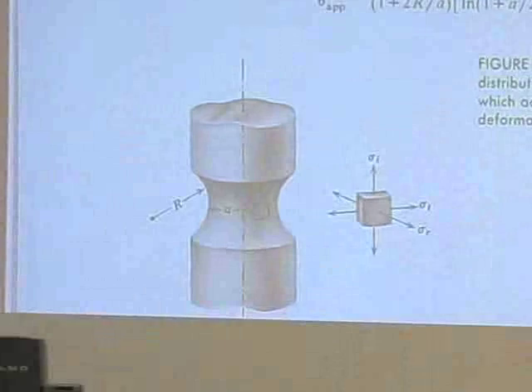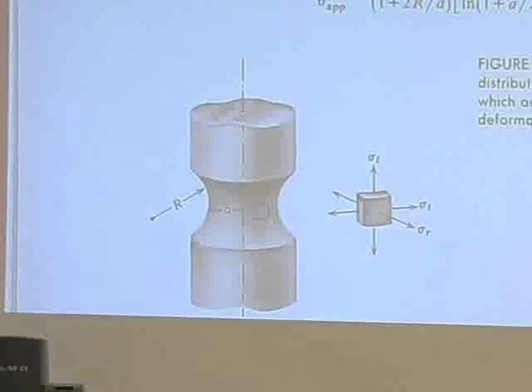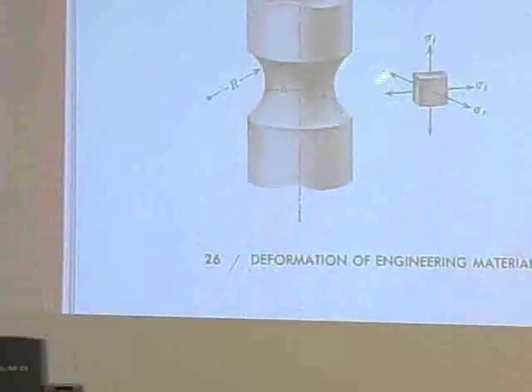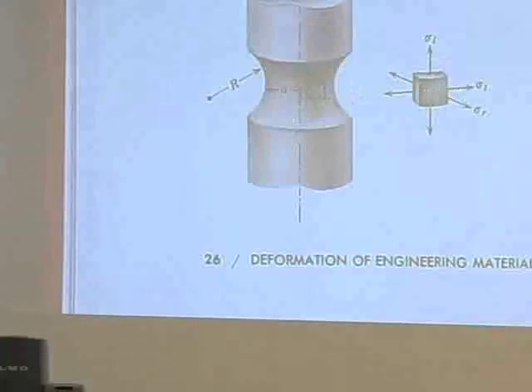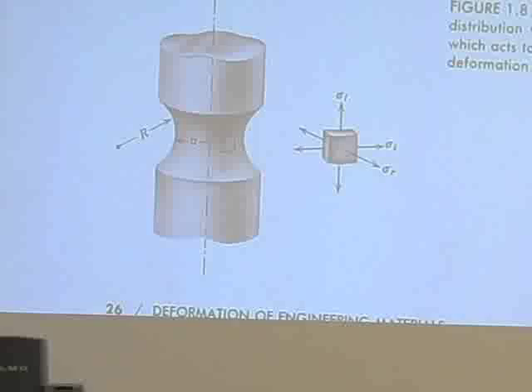it turns out, I mentioned to you what Backofen told me more than 40 years ago, that the longer you think about a tensile test, the more complex it gets. And it's a lot more complex than you realize. This is what Hertzberg talks about in a simple necking in a tensile test. If you look at a little volume element inside the neck, you'll find it's got stresses in all three directions. You've got unyielding material basically on either side, and that means that you will induce Poisson's ratio, giving you stresses in the other two directions. Even though you're doing a uniaxial tensile test, in the neck region it's triaxial. And so he actually says that, triaxial tensile stress distribution within the neck region.